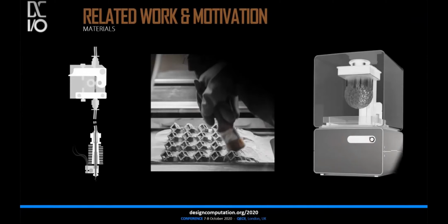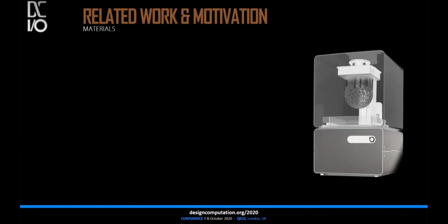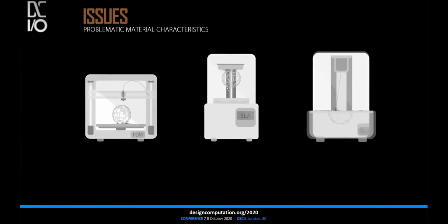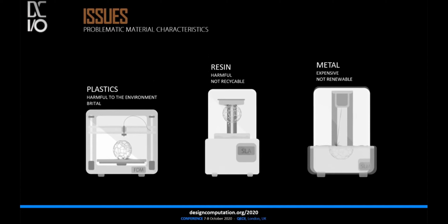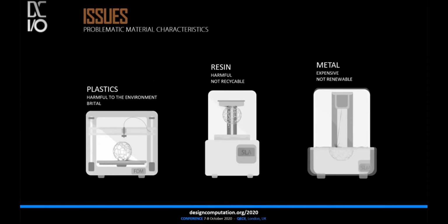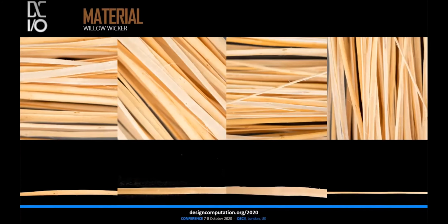Of course, there are several other types of additive manufacturing that use different materials such as resins or metal. While the process of printing is different, for example melting metal powder or hardening UV-activated resin, none of these materials can meet the aimed target of sustainability, but instead are harmful to the environment, not renewable or recyclable. As a new technique, we have developed an additive manufacturing method using a wooden filament made of a fast-growing local plant, wicker twigs. This technique enables direct and laminated wood filament extrusion without the use of thermoplastics.